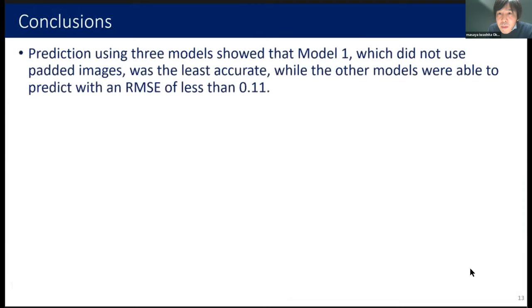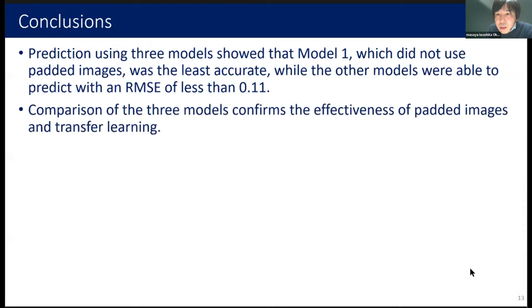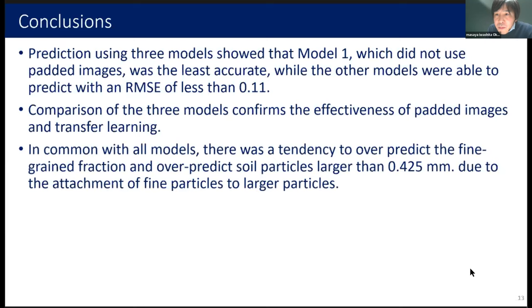The following are conclusions of this study. Comparison of the three models shows that the application of data augmentation and transfer learning improves RMSE. In particular, the two models to which data augmentation was applied produced predictable results with an RMSE of less than 0.11. In fine-grained soils, there was a tendency to over-predict the fine-grained fraction and over-predict soil particles larger than 0.425 millimeter. This may be due to the attachment of the fine particles to larger particles.